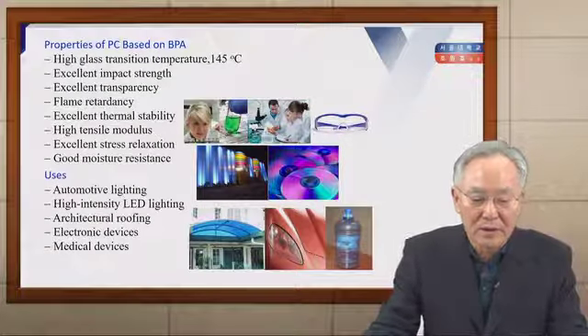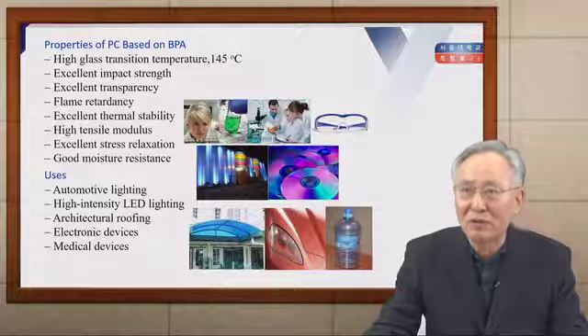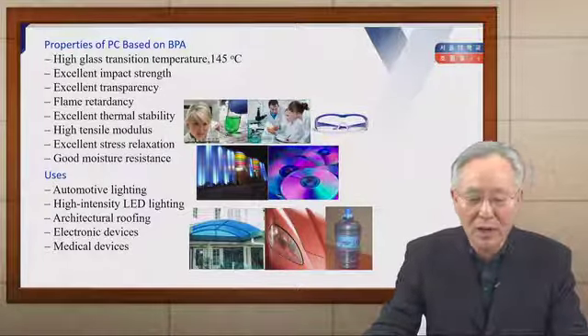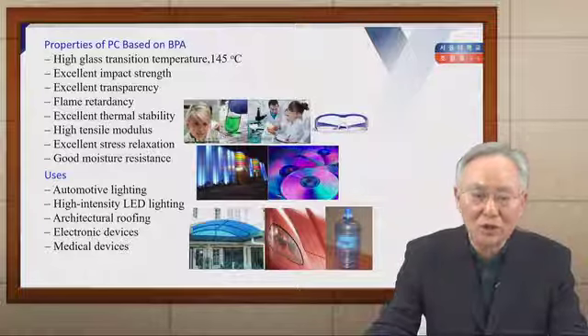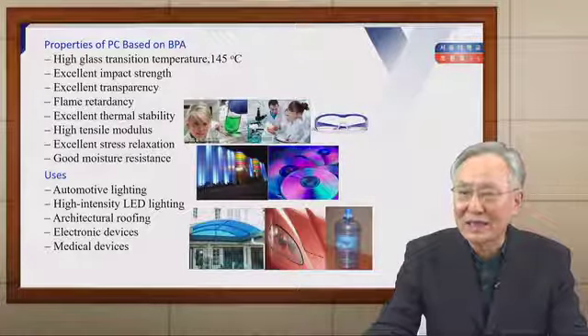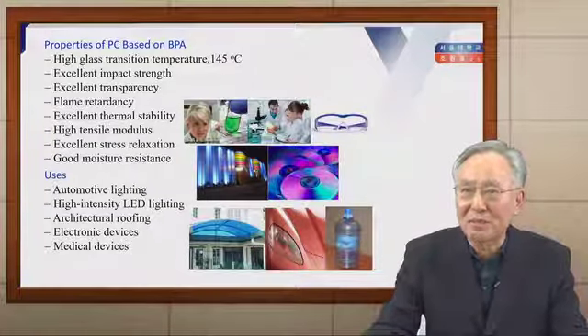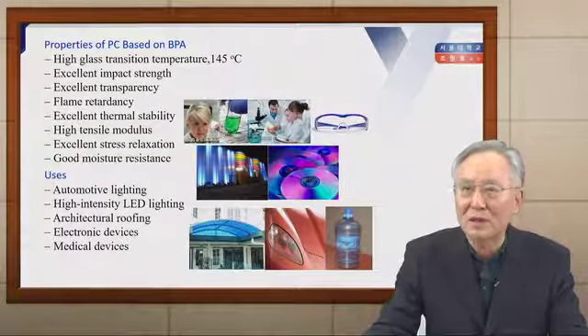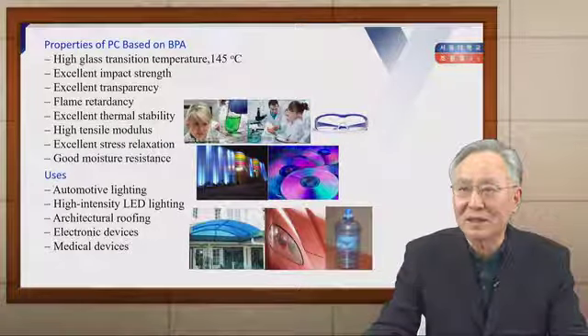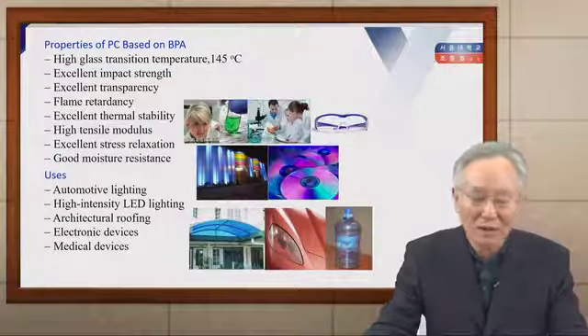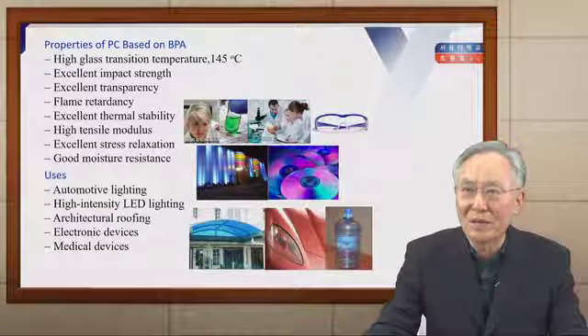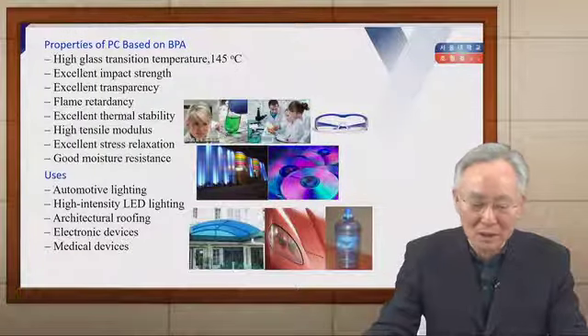BPA-based polycarbonate has many good properties, such as a high glass transition temperature of 145°C — much higher than that of PET or PBT. PC has excellent impact strength, excellent transparency, flame retardancy, excellent thermal stability, high tensile modulus, excellent stress relaxation, and good moisture resistance.